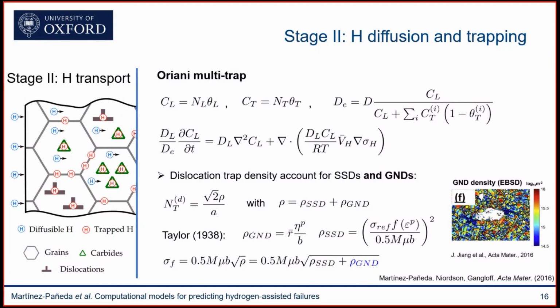So we know that typically most of the models that I've seen when it comes to hydrogen trapping at dislocations consider only the statistically stored dislocations that are related to plastic strains, but we should also consider GNDs, geometrically necessary dislocations, because we know from experiments that they are very significant and dominate dislocation behavior near cracks and inclusions. And therefore, if you want to quantify your hydrogen distribution at these locations, you need to be able to quantify these GNDs that are related to plastic strain gradients.